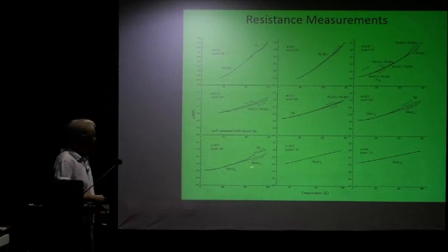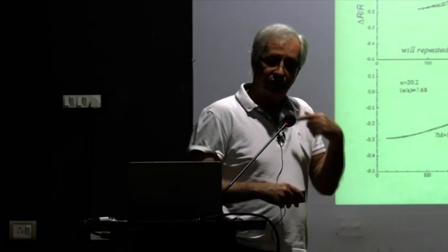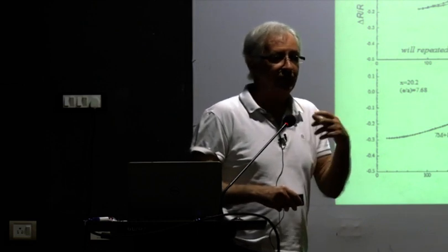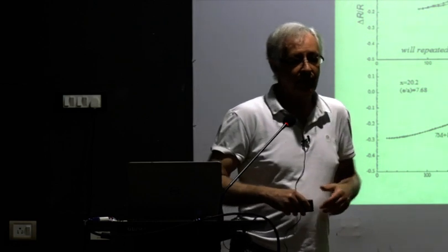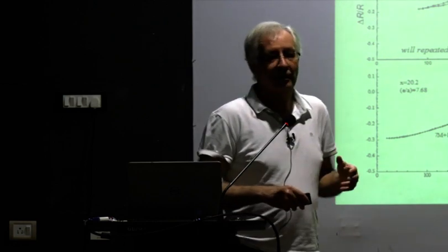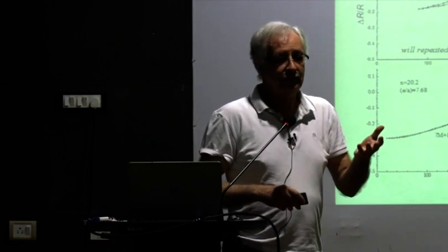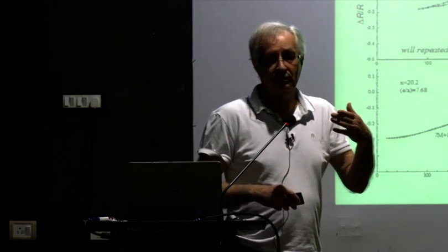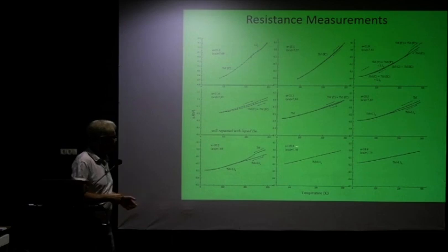We don't know. But you see that the resistance has decreased over here. And then you look at the consistency. Should the resistance decrease or increase? Well, L10 is a structure that is of higher symmetry than the modulated structure. So automatically what one would say is that if that is the case, then the scattering would be less, so that the resistance would be less. And things like that are consistent.